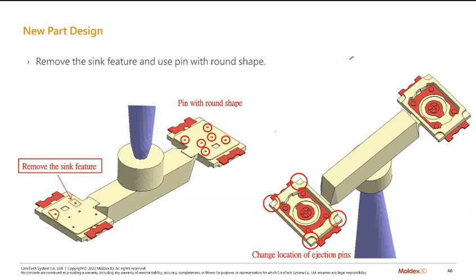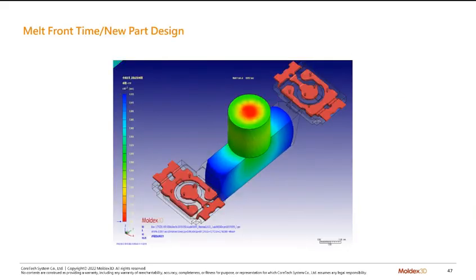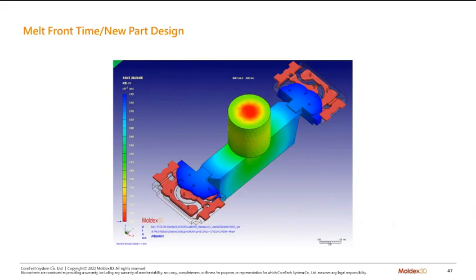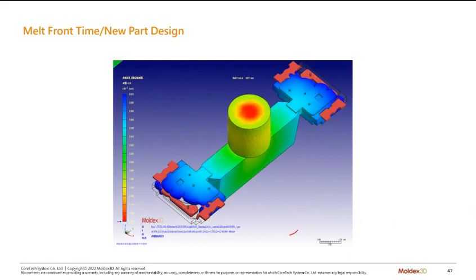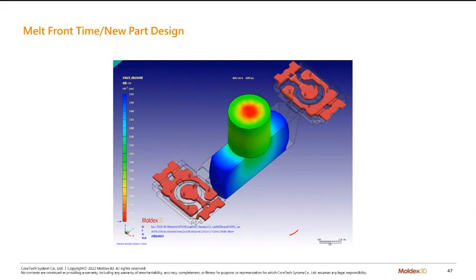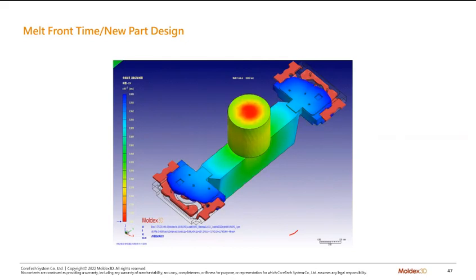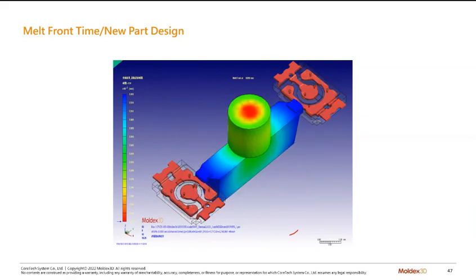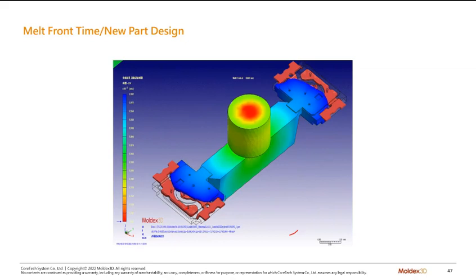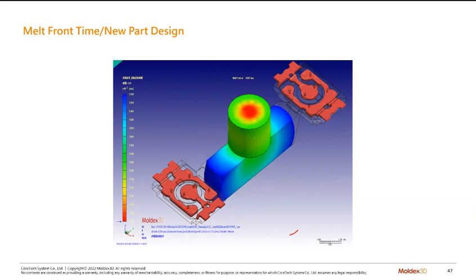So when the thickness becomes bigger, the melt front temperature will be higher when the two melt fronts meet each other. So if we check these ones, okay, for sure we have a pin here, and we can expect the weld line somewhere here. But once we remove the features and we have a more uniform thickness, it will not have a hesitation issue near the pins, and the quality of the weld line can be improved, and maybe they can fix their crack issues.